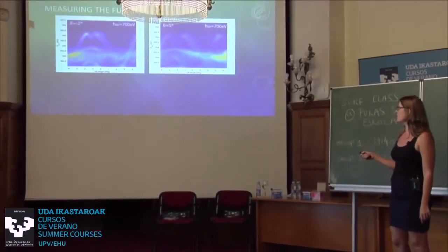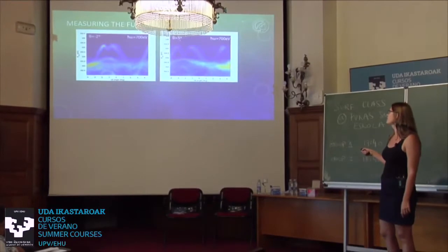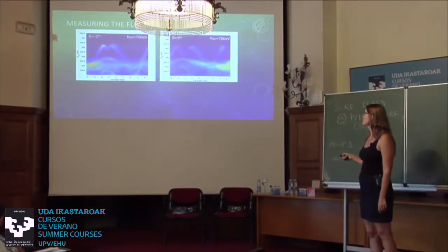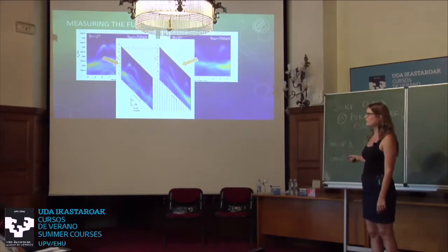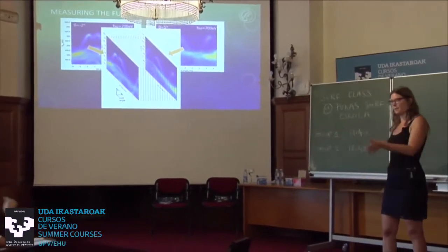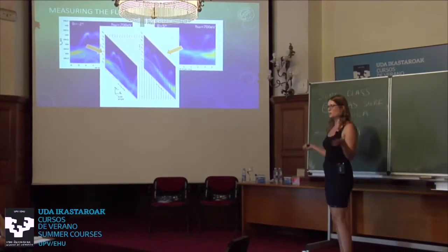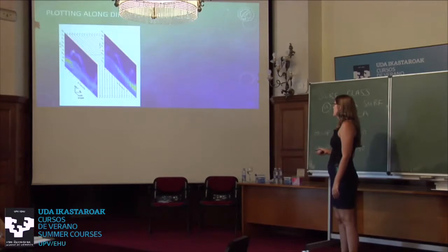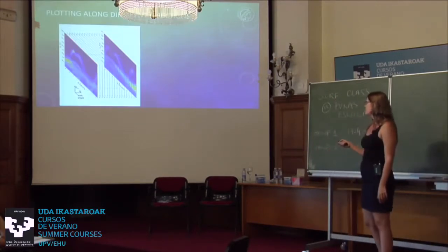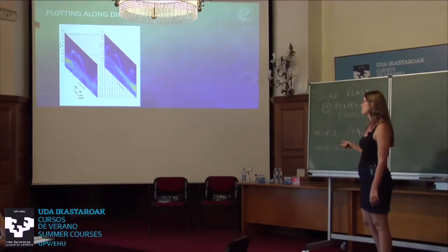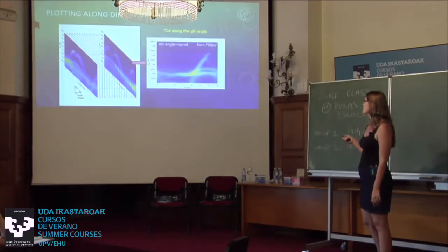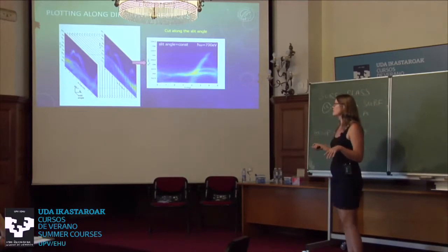And then this image is at one given tilting angle of the sample, and you can continue to tilt the sample, and you can get more of those images, and then you can put them all together to get a full data cube of slices to have the full Brillouin zone measured of your compound. And then you can also make plots along different directions if you take a cut like this, of course. So this is just one path along the Brillouin zone. If you want to plot a different path, you can cut all your images here, and you get different spectra. But note that here, the resolution of these spectra depends on how fine you tune the tilting angle and how many of those individual images you took, whereas along this one, you have a much higher, nicer resolution.